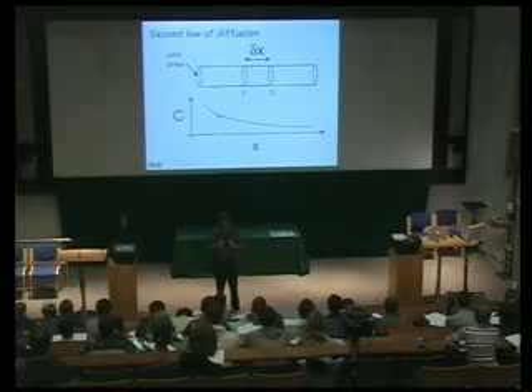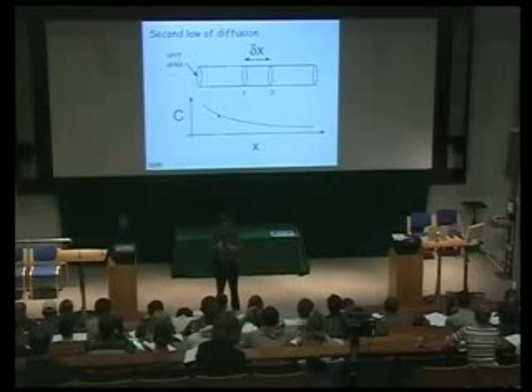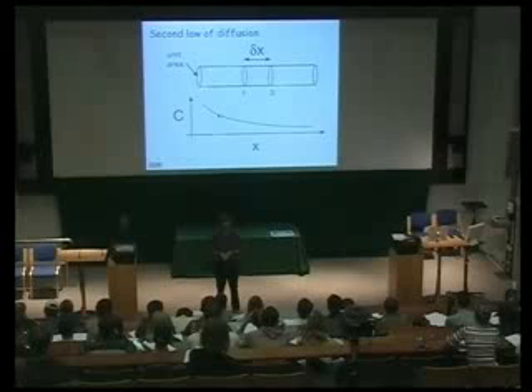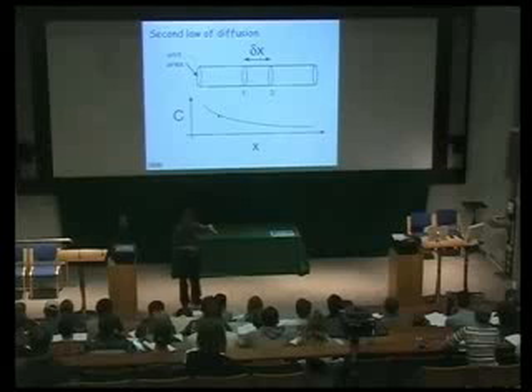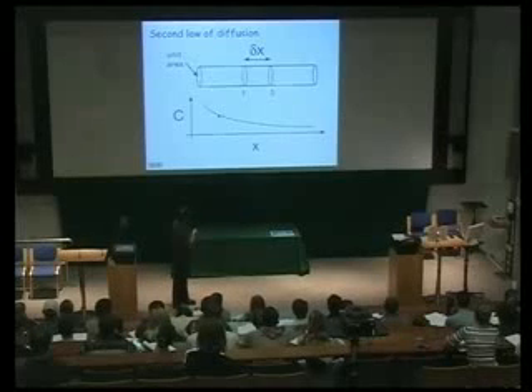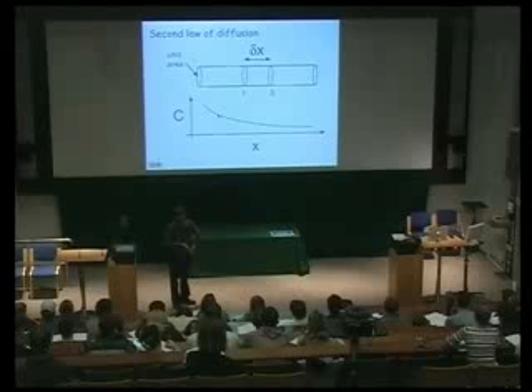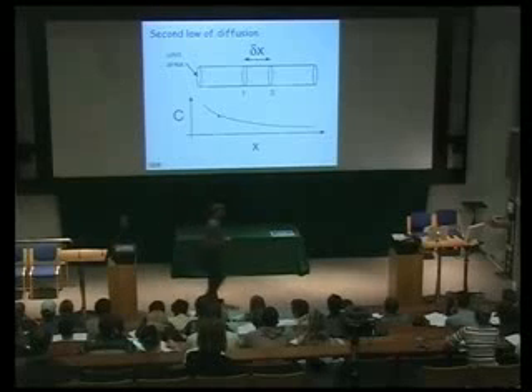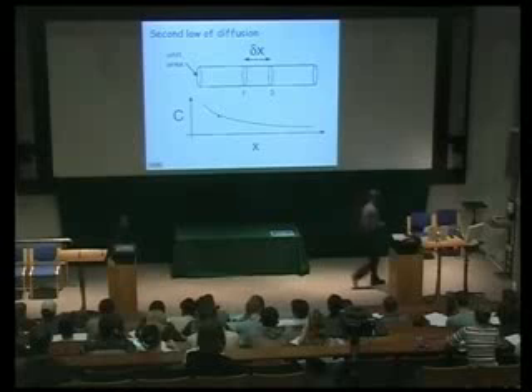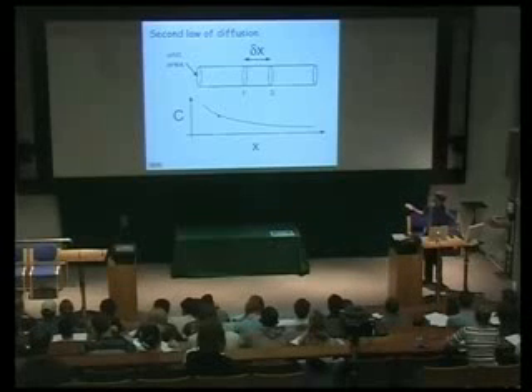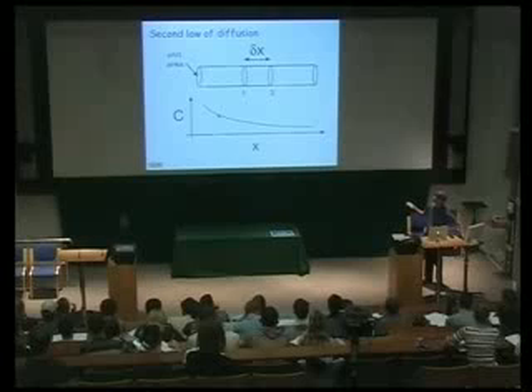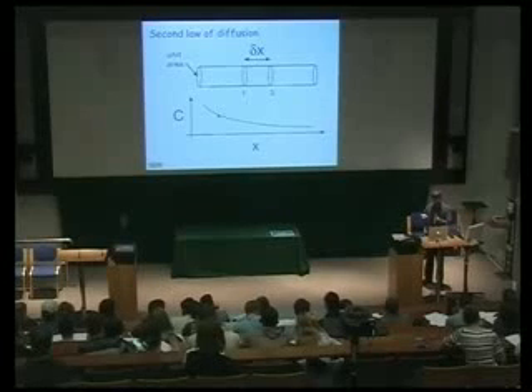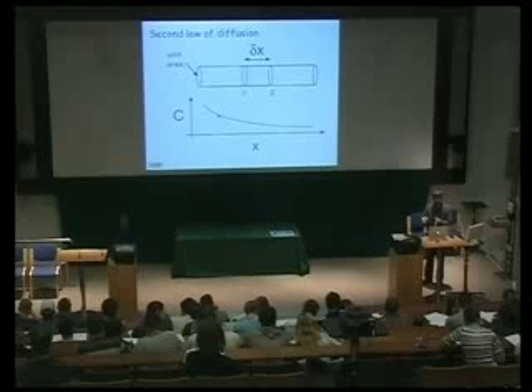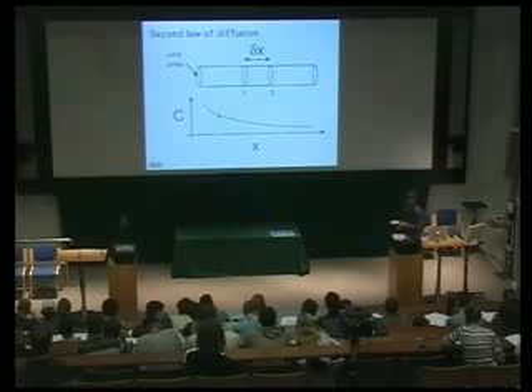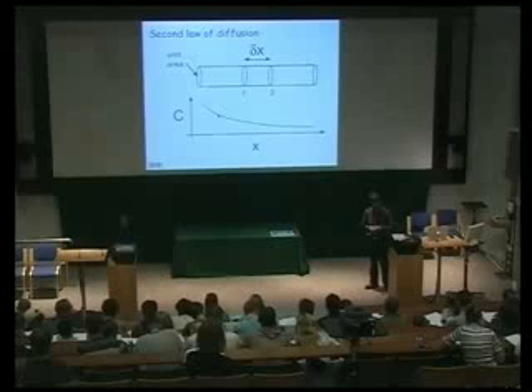So you've either got to get a buildup of solute or a depletion of solute, depending on how the concentration varies with distance. Okay? So no longer will the gradient of concentration remain constant. This will actually change with time. Okay? So what we are going to do is we're going to apply Fick's first law to this plane and then apply it to this plane and take the difference between the two fluxes. The difference between those two fluxes will tell us how the concentration in this region changes with time.